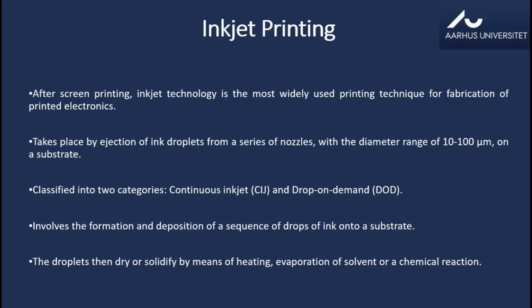A lot of these functional inks that I'm talking about are not just silver particles dispersed in a solvent. It normally is not that, because the dispersion of these nanoparticles is not very good. So you have to add a lot of additives, which are organic materials, or a lot of binders, which are again organic materials. And when you are printing, your droplet will have all these materials. So it will have the solvent, it will have your metal, for example, let's say silver nanoparticles, and then all these binders and additives.